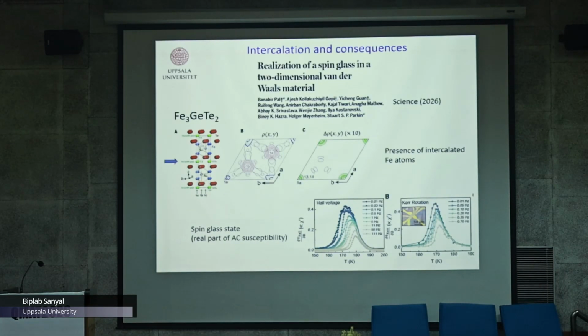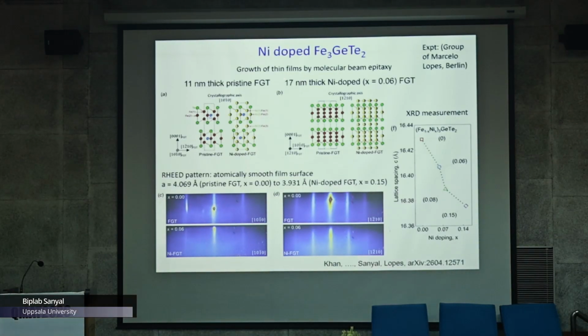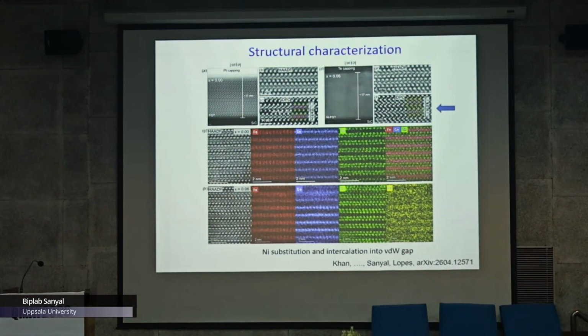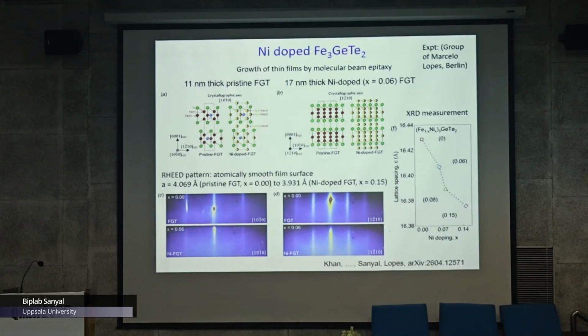What we have is iron germanium telluride, but with nickel doping here. Our experimental collaborators have synthesized this material by molecular beam epitaxy in Berlin. So they have this pristine FGT, as I call it for short, and they have this nickel doped FGT, shown in two different ways.